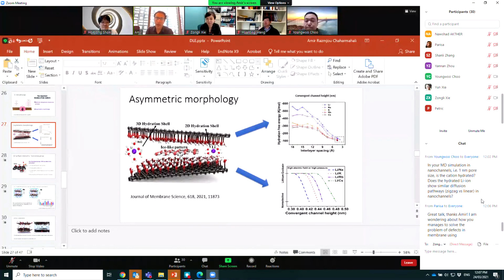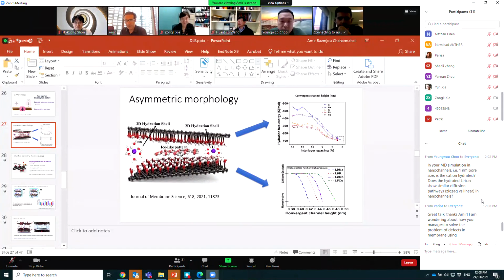Well, maybe I want to correct your question. We don't have full dehydration, because it's going to be dry. So we have a partial dehydration. There is some literature where people found that there is a dry transport of protons, so we can transport protons in a dry way. However, for ions, it's very difficult. In particular, it's very hard because you need to have some hydration for them to transport. So for 1 nanometer, even below 1 nanometer, if your membrane has ionic conductivity, you need to have some hydration. I'm not sure I answered your question. Yeah, it did. Thanks.